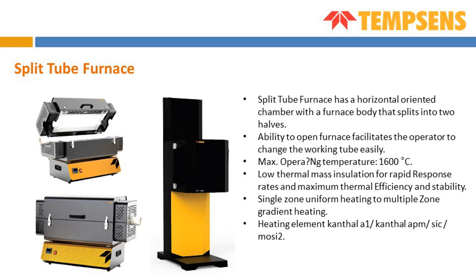And the temperature we can reach in a split tube furnace is up to 1600 degree centigrade. Based on temperature, we can change our heating element. For up to 1200, we use Kanthal heater. Beyond that, silicon carbide up to 1500 degree centigrade. Beyond 1500 degree centigrade, we go for the molybdenum heater.